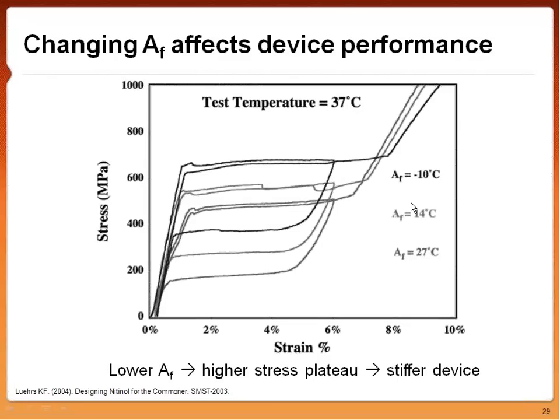What that basically illustrates is this. We see a phenomenon where you can change your AF temperature and you change your stress plateau. And that's actually happening based on our material properties. So when we have a higher percentage of nickel inside our nitinol matrix, we can actually lower our AF temperature. And in terms of a device, we can have a higher stress plateau, meaning you're going to have a stiffer stent. In turn, when we take nickel out of a nitinol matrix, we can actually increase our AF, and we can have a lower stiffness for our stent.